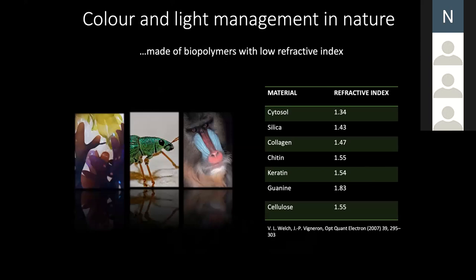What is important for the production of color is a material property called refractive index. I don't know if you have come across it, but as a physicist, you might know that in order to be more efficient at interacting with light, you would want this refractive index to be pretty high. Generally, if you use inorganic material, you can obtain really high refractive index. But with organic material, polymers and biopolymers, it's generally not easy to obtain high refractive index and so strong interaction between light and matter. So it is surprising that nature can optimize the structure so much, because you have to compensate for the lack of the ideal material. But nevertheless, you are able to obtain a structure and an optical appearance that are pretty impressive.